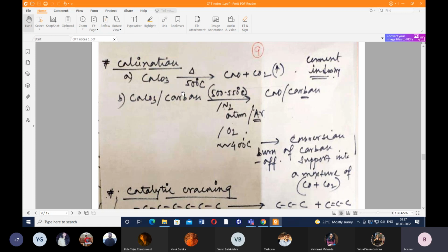So in the next step, people take a certain amount of material, say for example, 100 milligram of that material, placed inside a U-tube quartz cell, okay? And after that, they purge hydrogen, 5% hydrogen in 95% nitrogen, through this material and allow the reaction to continue from room temperature to a certain temperature, let's say 900 degrees Celsius. Okay, so at a certain point, we'll get a peak. So we'll have to take that peak maxima.